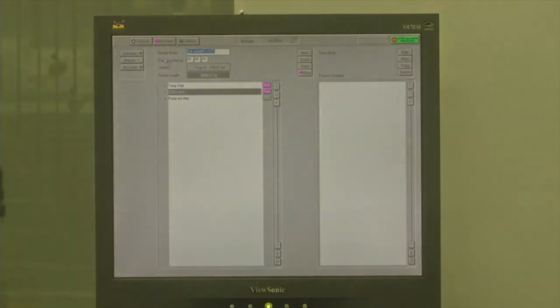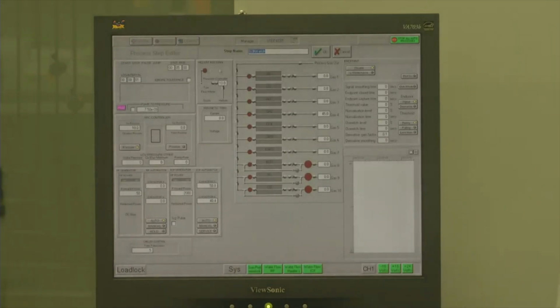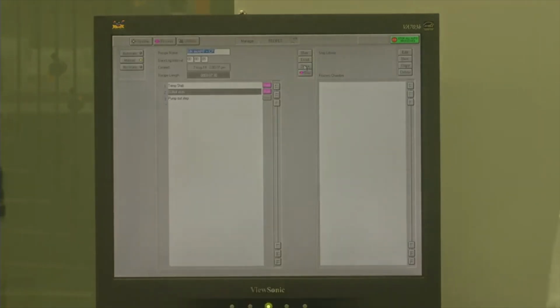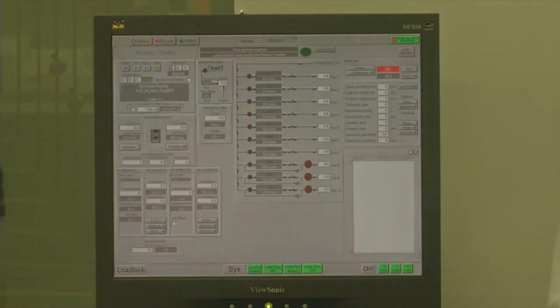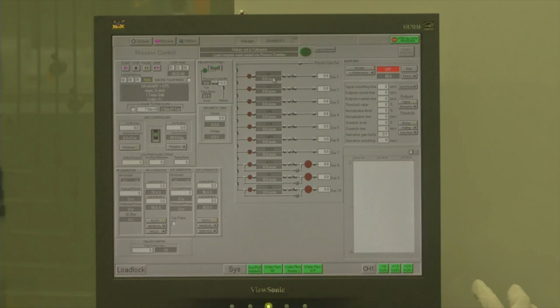Once the loading is done, we have to select the right recipe to etch the nitride. What you see here is a nitride etch recipe where various gases are present, and we are going to run that particular recipe. You can see there are various gases present in the system, and we have chosen a certain gas to flow through. We have to maintain the right time for that particular etch, and also the pressure required to do the etch.